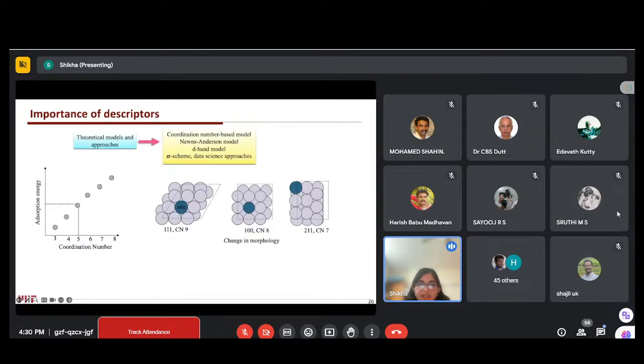Now, why are these descriptors, or given properties, important for designing the material? Suppose we pick a property like coordination number, which we can calculate just by counting the number of atoms around the site. Here we have a site coordinated by 9 atoms. This is the 100 surface, where we have coordination number 8 for the site, and on the 211 surface we have coordination 7. So once we change the coordination number around the site, we change the activity of the site, like we change the binding energy of the site. Here the binding energy would be higher, here less, and here the binding energy will be even higher, so the site would be more active.